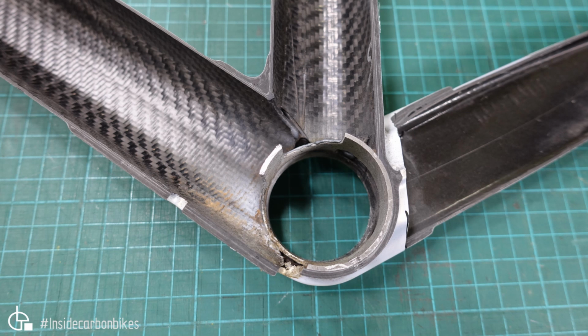So bottom bracket, this one looks a little bit better in that it doesn't have the void down here, which the other one did. So that's no big void there. It still has a little void here, which we'll have a closer look at a bit further down the track. And it's also got some dirt residue through here like the other one did, but the bottom bracket's bonded in well. A little bit of wrinkling again through these lug roots, but very similar to the other one, marginally better in that it didn't have a void.